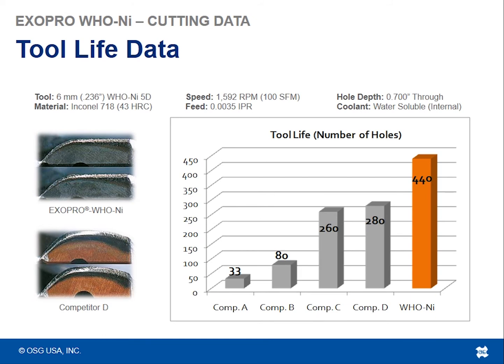So you can see that the WhoNi drill by far has the most holes, 440 holes over the nearest competitor, D. And then you see in the pictures on the left-hand side that nearest competitor, competitor D, how much wear it had versus where the WhoNi was at 440 holes. So while the wear amount looks the same, the WhoNi, in fact, at this time when the picture was taken, already has 440 holes on it versus that competitor D with only 280.